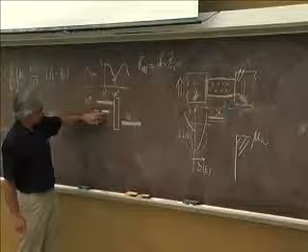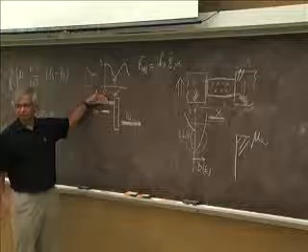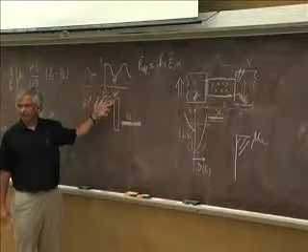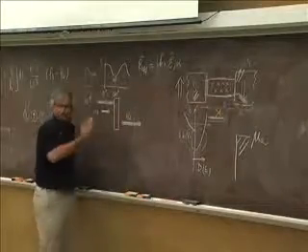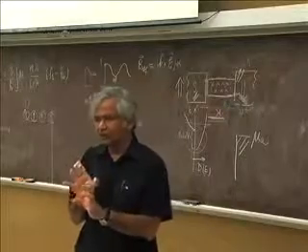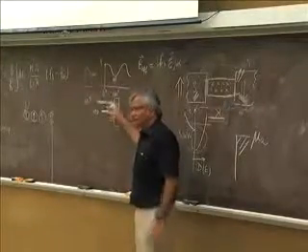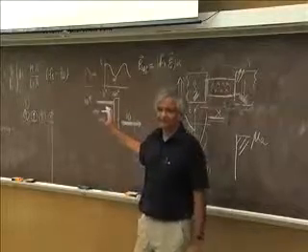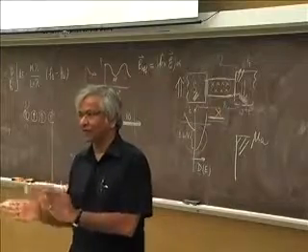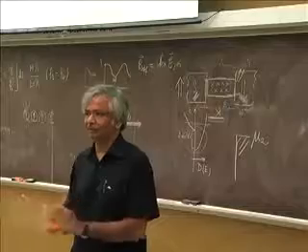But then, after some time, this guy won't be able to fill it anymore very well, but this will still be able to, because 10,000 lanes, even working not so well, can still fill it. And then you'll start seeing a difference around here. That's my understanding of this. And again, these are things, if you're just doing a pure quantum mechanical simulation with same number of lanes, etc., you may not necessarily get it out of that. You see, so a lot of things from common sense looks like that's what should happen. If you did a simple classical treatment, you'll get it, but the full quantum mechanics might miss it.